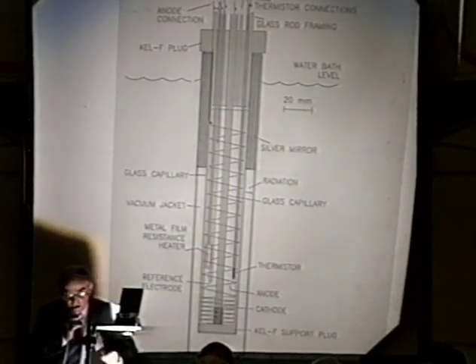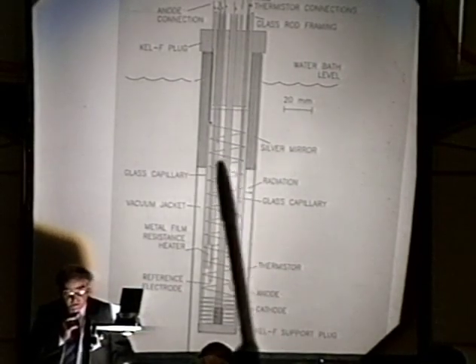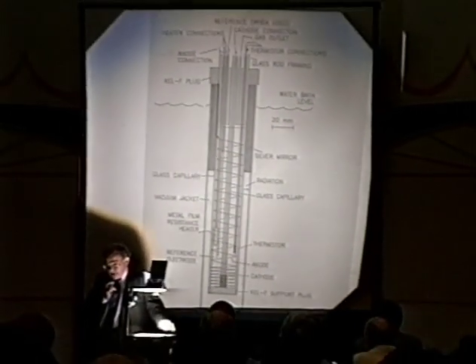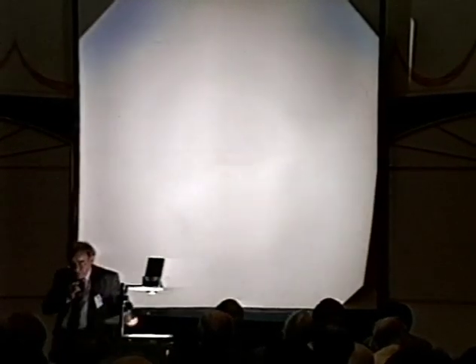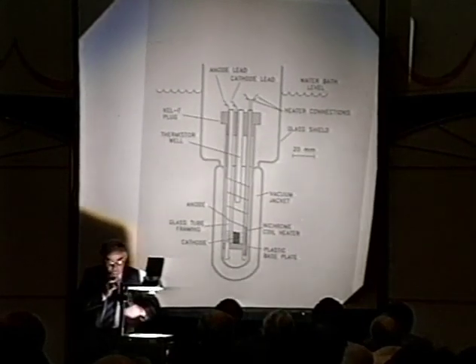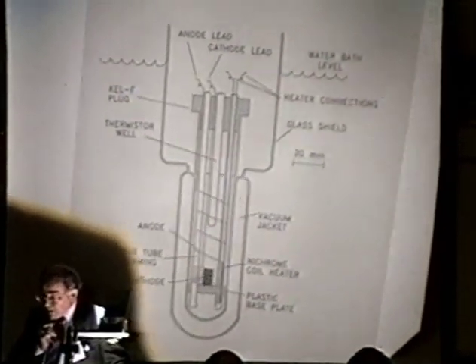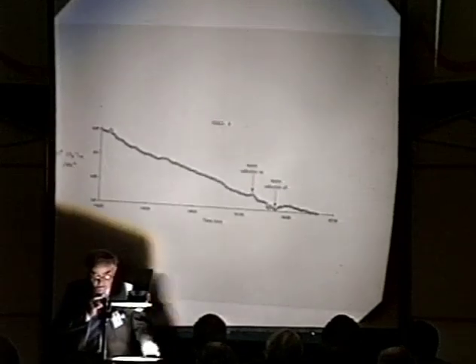This is our cell, our recent version of the cells we've used since October 89, with silvering at the top to remove the tidal effect as far as we can. And this morning I showed you can really keep the heat transfer coefficient constant to 1 part in 1,000. But in the Harvard cell, which had all this glass on the top, and there was no silvering, of course we expected to see a change in the heat transfer coefficient with time. And that's what we do. You see this change in the heat transfer coefficient with time, this decrease.